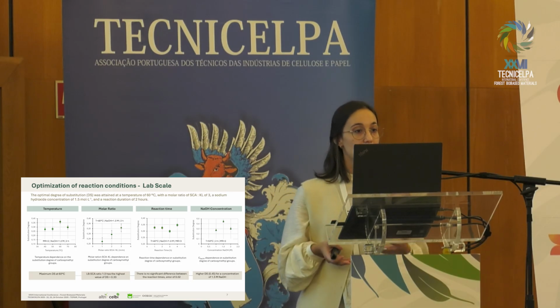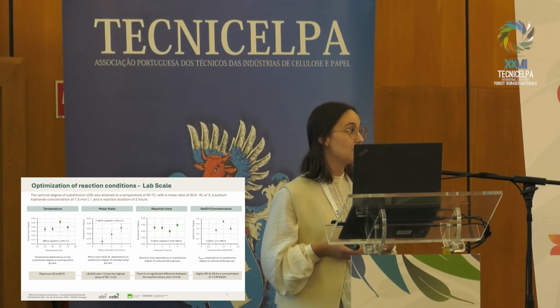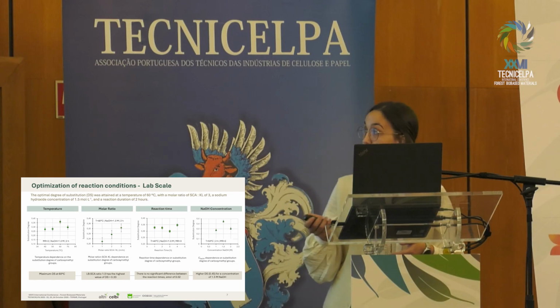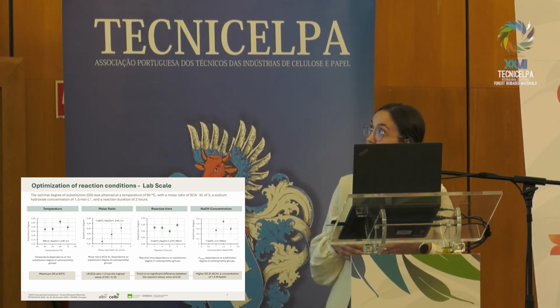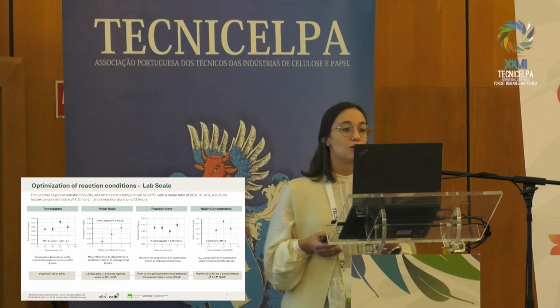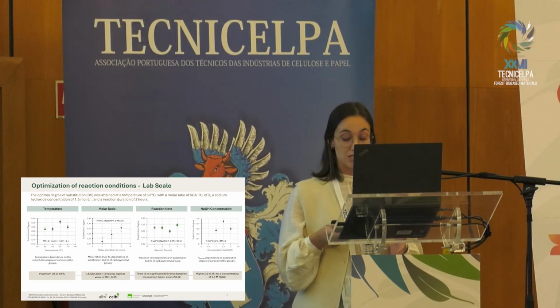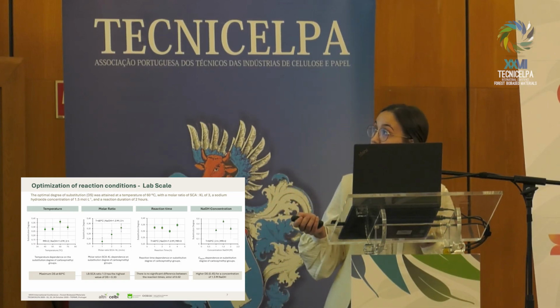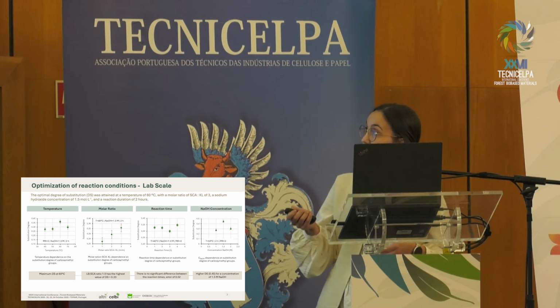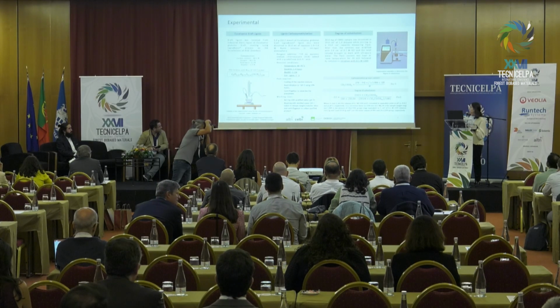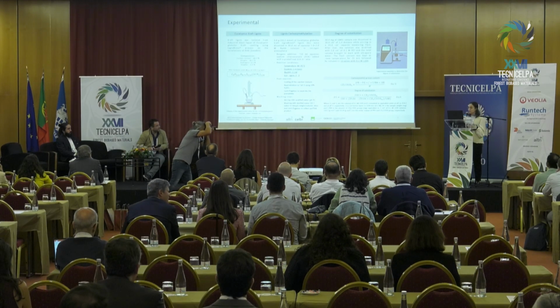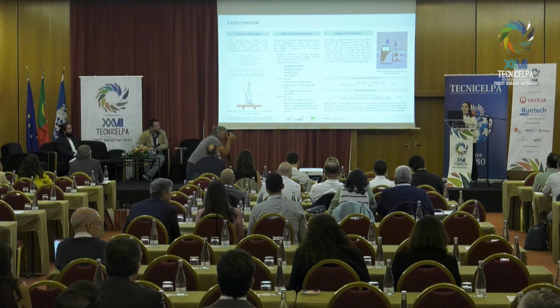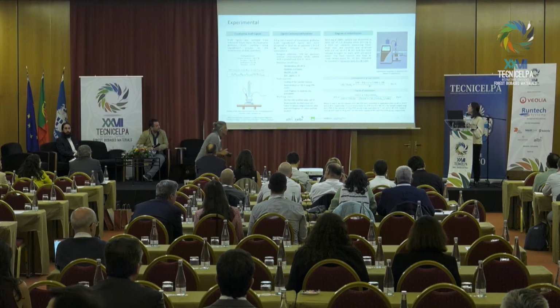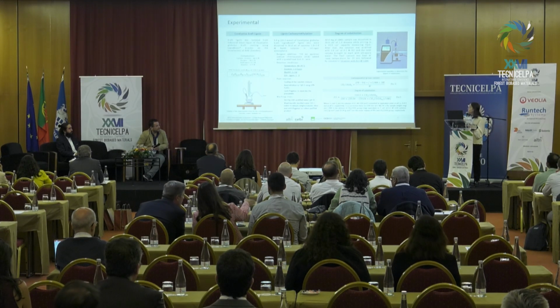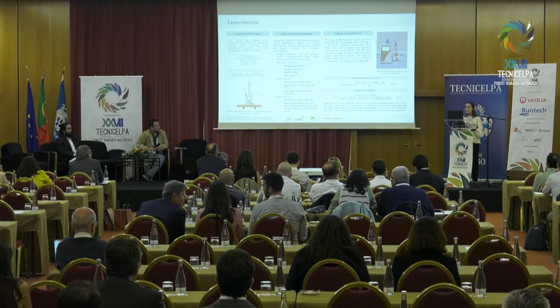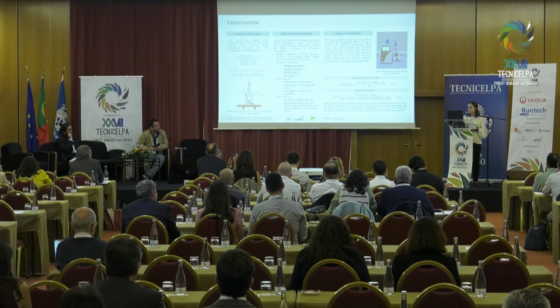To do so, we used a eucalyptus KRAFT lignin, which was isolated by the LignoBoost process, and it was previously characterized. Lignin carboxymethylation occurred under alkaline conditions, and we focused on optimizing 4 key parameters: temperature, time of the reaction, sodium hydroxide concentration, and sodium chloroacetate to lignin molar ratio. After each reaction, we measured the degree of substitution using a potentiometric titration, using methods already described in the literature.